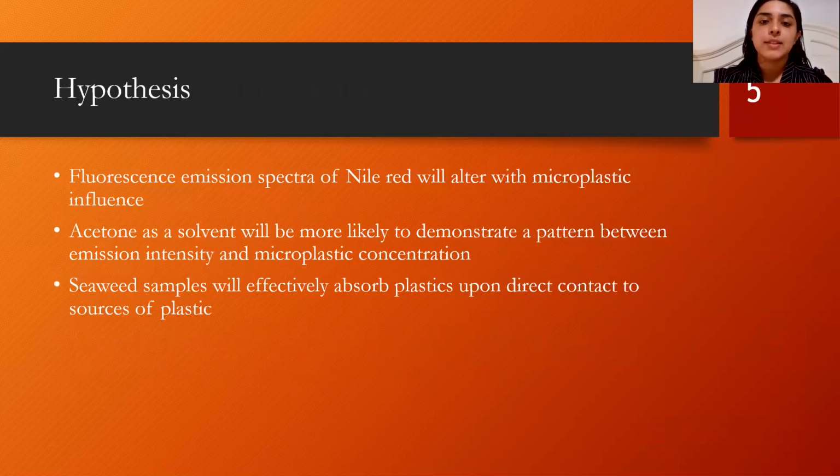So several hypotheses for my own research were that fluorescence emission spectra could potentially demonstrate a direct relationship between microplastic concentration in a solution and emission intensity. For this, I had to consider various solvents, and the two that I used for my own research were acetone and methanol. Methanol was anticipated to have very little interaction with the plastics in solution, whereas I anticipated acetone to have an increased interaction either through degradation or potential dissolution.